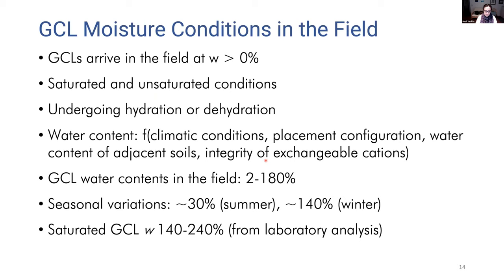Based on field studies, geosynthetic clay liner water contents in the range of 2 to 180% have been reported. Seasonal variations also have been reported. A variation between 30 and 100% between summer and winter is reported for one case in a cold, humid climate, and shows a large range of variation in the moisture content of the material at the field scale. For most cases, the 2 to 180% range is the overall range.